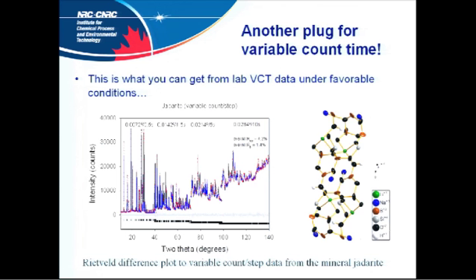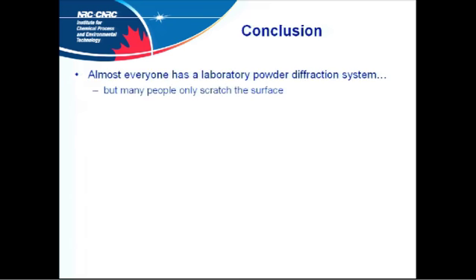And I will give another plug for variable counting. This seems to be a topic of the moment. This is just an illustration using some mineral which some people may recognize. Basically increasing the count time. And you can also optimize your experiment time by increasing the step width with angle, because the peaks get broader at higher angle, so you don't need as many points to cover the peak. Conclusions.